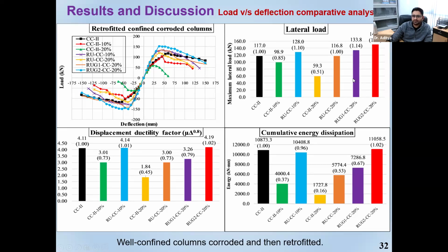Then the question arises: why are we going for GFRPs? The reason lies in the ductility response. This is only the peak response that I am giving to you, but the post-peak response is also very important when it comes to having a good seismic response, because that's where we are focusing on, right? So though we recovered the load, you can conclude here that if you want to recover only load, you can just go ahead with the UHPFRC retrofitting, even if the column is corroded for 20%. But if you see the ductility factors over here, it was not recovered. It's the same column over here, retrofitted with UHPFRC at 20% corrosion. You can see it's 27% lower than the control. So we had to add extra GFRP layers in order to come to its point.